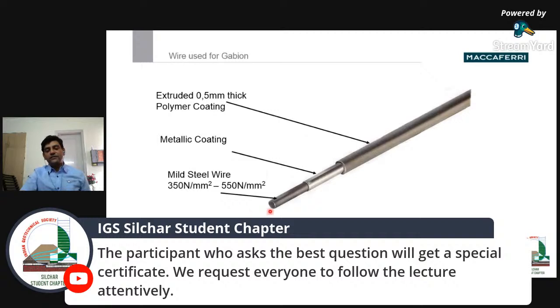The requirement of this steel wire is usually that the elongation at break shall be more than 10%. If you are going to construct a structure with this steel wire and it has to be durable, there are possibilities of corrosion. So corrosion protection is provided with a metallic coating. Typical metallic coating is galvanization using zinc, or now there are advanced coatings of zinc aluminum alloy, referred to as Galfan coatings, which have 3 to 4 times more resistance than just the zinc coating.